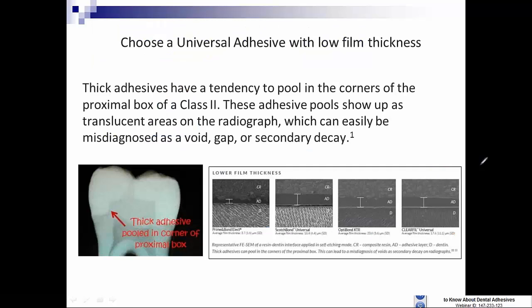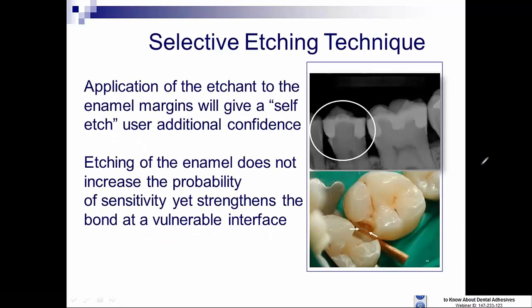Now, the universal adhesives have a variety of film thicknesses, and low film thicknesses are advantageous to us clinically, number one, because high film thickness adhesives can fool us in postoperative radiographs that look like voids or look like recurrent caries, but often are pooled adhesive, particularly in the corners of sharp cavity preparations. And so we can see in these photomicrographs that other universal adhesives such as Clearfil, Optibond XTR, Scotchbond Universal have significantly higher film thickness than the Prime&Bond Elect, which is a very thin acetone containing material.